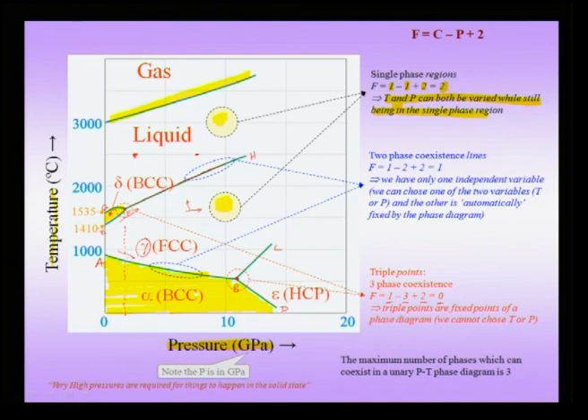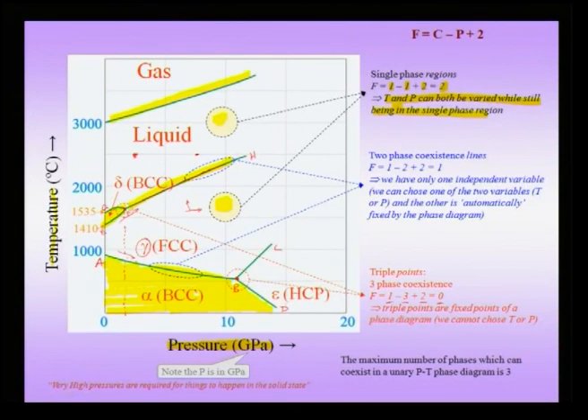The manner in which the lines are sloping is important to note: the coexistence lines demarcating the gamma form from the BCC form slope upward, while the FCC–alpha boundary slopes downward. The gamma phase field — the close-packed phase field — expands on increasing pressure, which is not surprising, because at higher pressure you would rather prefer a lower volume, which is provided by the gamma form of iron. Compared to the liquid state, the solid state has higher density, so at higher pressures the liquid–solid gamma boundary slopes upwards.